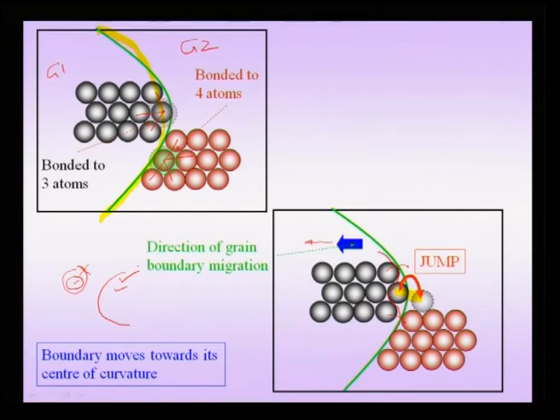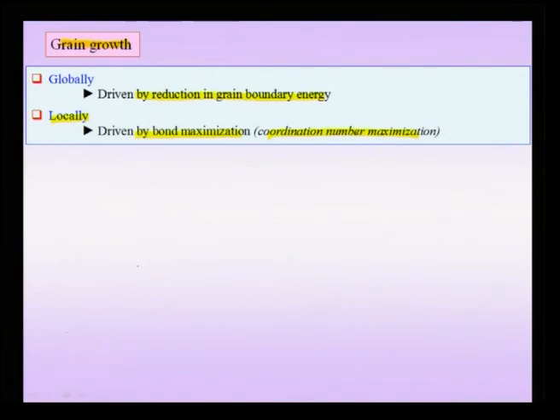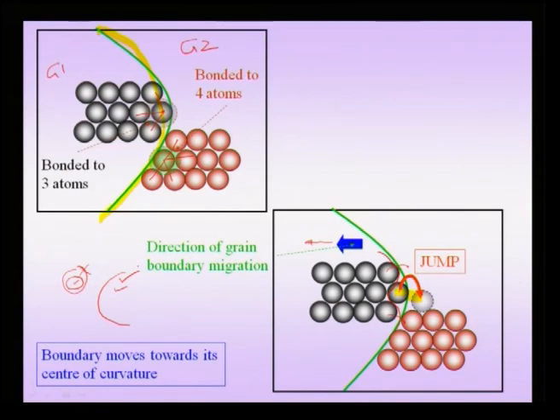So we have seen that this grain growth is not driven only by the global criteria, but also by the local criteria, and the local criteria involves the jump of atoms which are poorly bonded to neighboring grains where they can be better bonded. That means the system energy can come down, and in the process the grain boundaries tend to move in such a way that the smaller grains tend to shrink and the larger grains tend to grow, and in other words the boundary moves towards its center of curvature, causing smaller grains to vanish and larger grains to grow, and the overall number of grains hence comes down during grain growth.